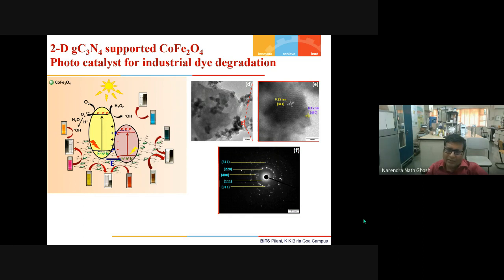We have done the HRTEM study and measured the fringes. We have done selected area electron diffraction. We identified the diffraction spots and we understand that this material consists of graphitic carbon nitride and cobalt ferrite. Let me share with you, we have done all sorts of analysis like XRD, Raman, TGA, XPS, and I have also shown you some FESEM and TEM to establish the structure of this material.